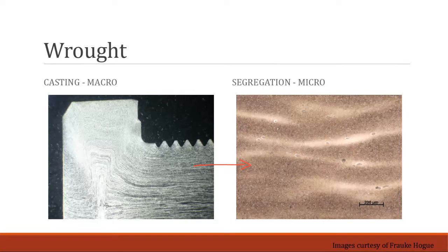So one of the things that you note are these little dull gray inclusions in your material. This is a steel. Those are likely manganese sulfide inclusions. They tend to be sitting in an area where the response to the etch was light, versus the areas above it, which are darker. So that's where you get chemical segregation within the material.